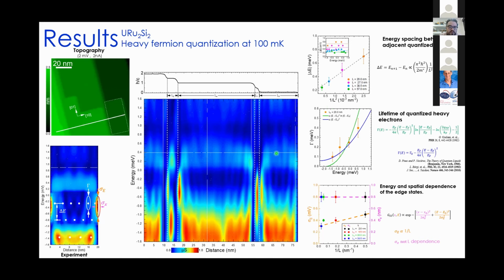This work is in progress, so the message to take home is this: we have experimental evidence of the quantum confinement of a heavy fermion system on the surface of uranium-ruthenium-2 silicon-2. I forgot to say that all these measurements were done at 100 millikelvin.